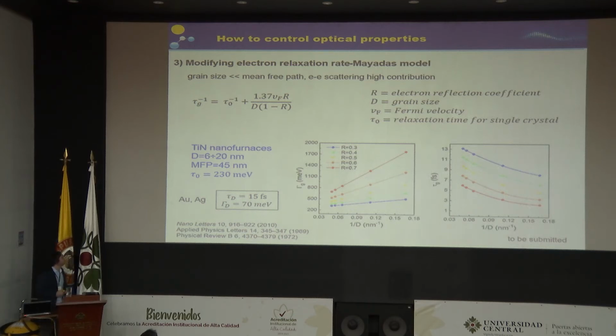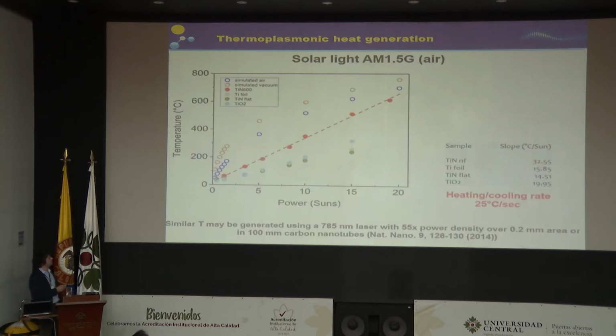As we can see here, by using this simple expression, we can calculate the electron relaxation rate for the plasmons inside our materials. We can see that for the smallest crystal size that we obtain, we achieve a really high electron relaxation rate compared, for example, with silver or gold, which has usually been reported to be 50 or 100 milli electron volts. This of course means that the quality of our plasmons is not very high, but also that we have really big dissipation inside the materials that can be used to produce heat, for instance. And so we use these materials to produce solar heating.